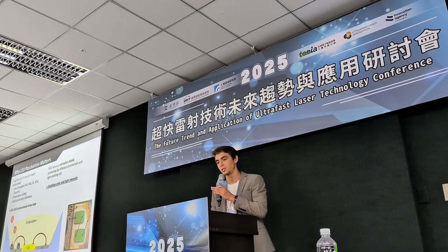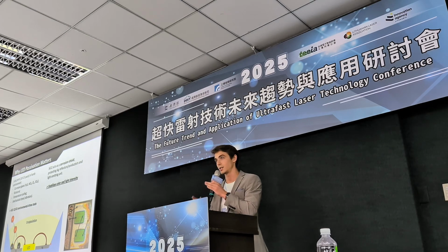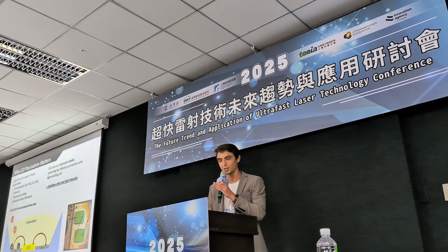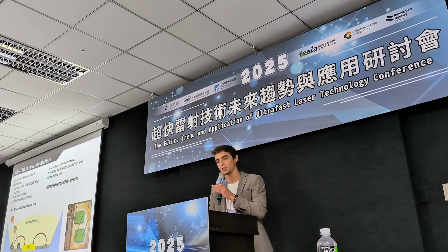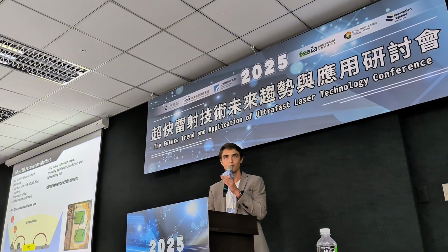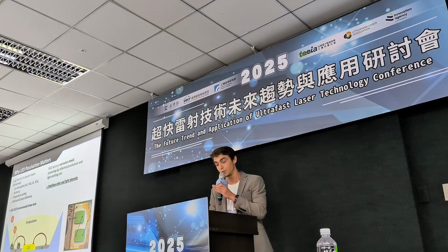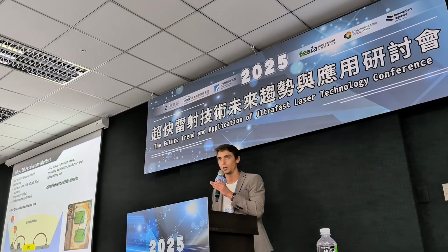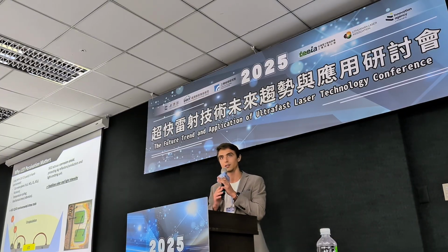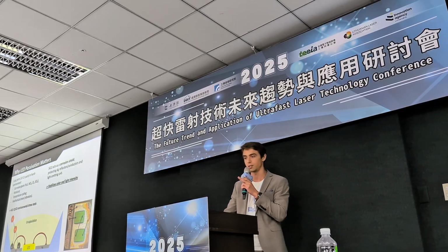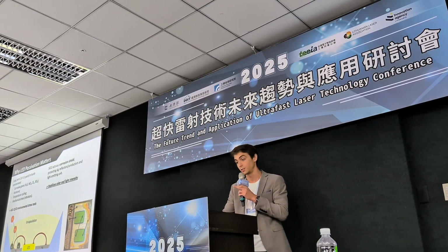When we need a long lifetime, we come to the situation where encapsulation cannot guarantee protection, because in the long term we need to consider slow processes like diffusion. In the long term, encapsulation becomes transparent for small molecules like hydrogen sulfide or hydrogen oxide, and through time they can diffuse through the encapsulation and react with, for example, the silver reflector layer. Silver reacts very well with hydrogen sulfide, forming not a bright mirror but a yellow, brown or dark layer. That first of all changes the color of the LED, and second reduces the light intensity coming from the LED. Light intensity could decrease by at least 50%. That is not a good condition.